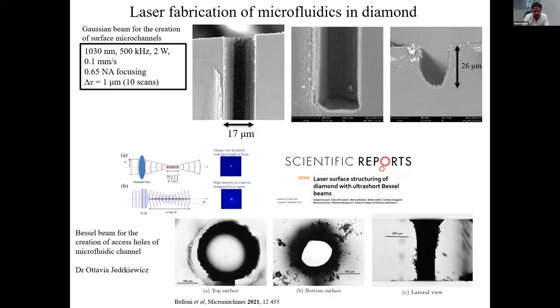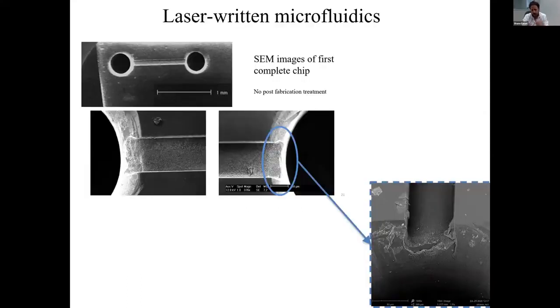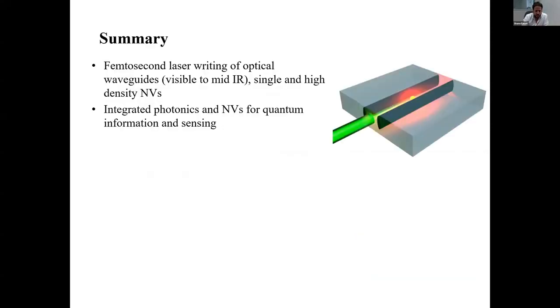And the idea is combining these two in a microfluidic chip, again, also with NV centers, and that's ongoing work we're doing with Ottavia. Here we see the next step of combining the laser-written microchannel formed with Gaussian focusing, and then these through holes, which have the appropriate size for connecting with microfluidic tubing. You can see very nice SEM pictures of these microfluidics.